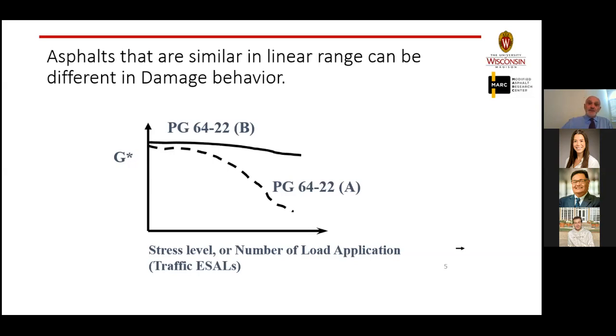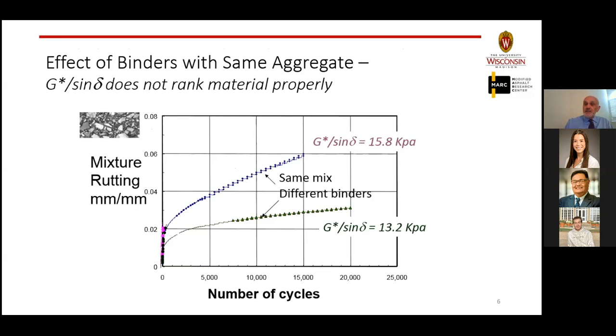There was a focused attempt to simplify the specification by looking at the linear range. Because once you go to nonlinearity, people are going to ask you, well, which stress do you want me to measure at? And how long should I be increasing the stress until failure and so on. So we all recognize that damage behavior is much more complicated to capture in a simple specification scenario. But it appears that we have no choice. If we don't go to the damage behavior, we will miss the opportunity of ranking different materials in the right way.